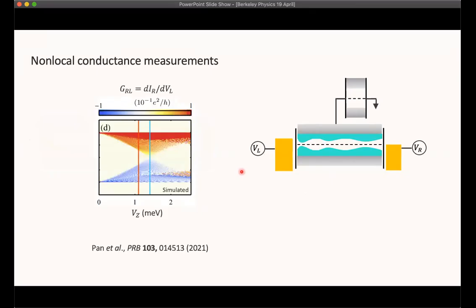And so if we simulate what we might expect in the case of a topological phase transition observed through such a wire, where again, we're measuring the change in current on the right side with respect to change in voltage on the left side, then what you see is a gap again. And now you can interpret this gap not as some disordered gap locally, but as the smallest gap that extends the entire length of the wire. And that gap closing should now indicate to you a bulk gap closing of the entire wire. And reopening should equivalently tell you what's happening along the entire wire as well.